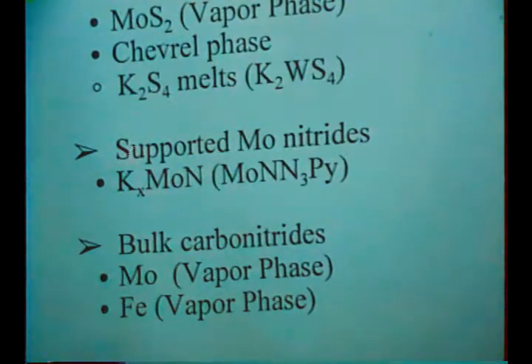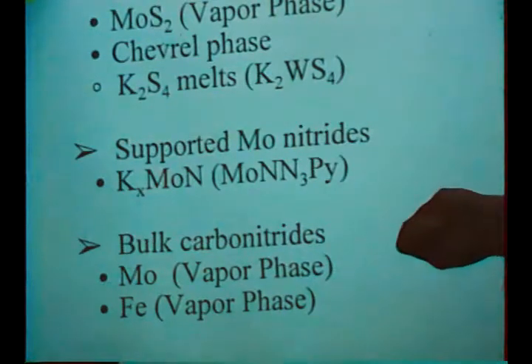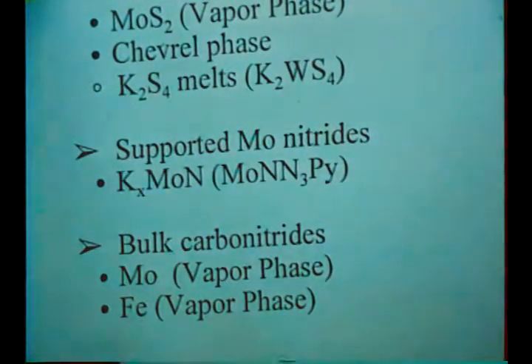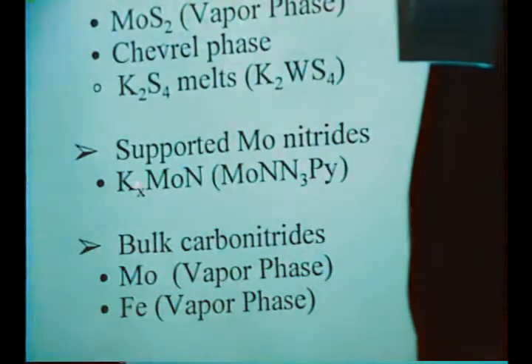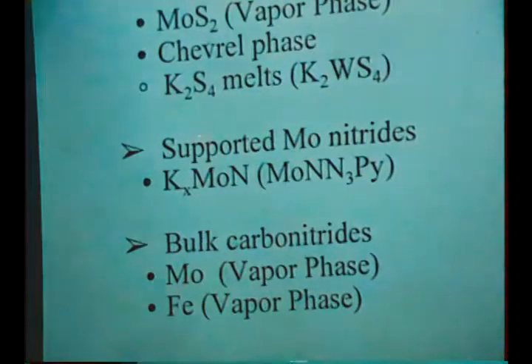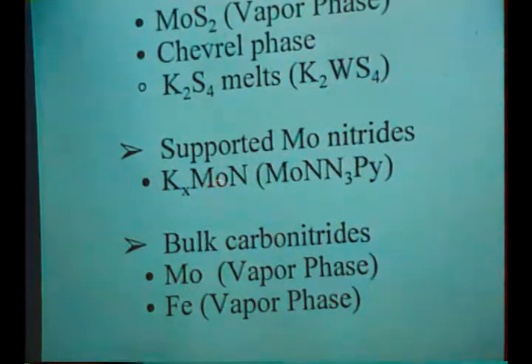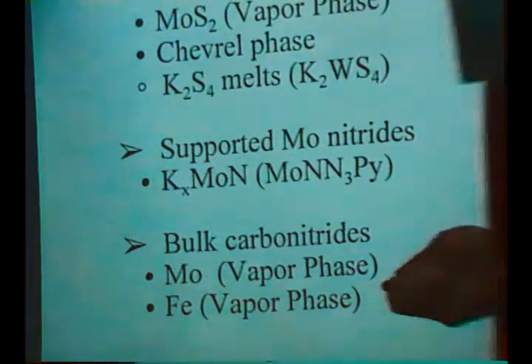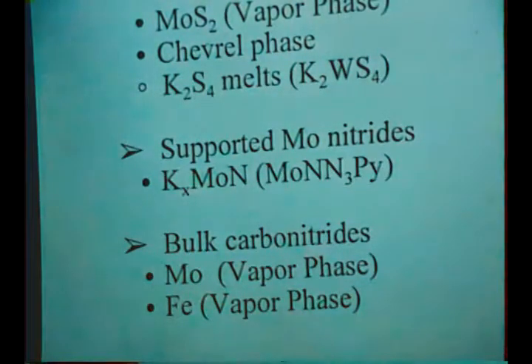The third area is making supported molybdenum nitrides. Now, this process was initiated with some work I did through graduate school with a molybdenum azide compound that is soluble in pyridine dichloromethane that can be then supported on supports and alkalized to make a potassium or cesium doped molybdenum nitride, supported molybdenum nitrides. This is a fairly unconventional approach to the nitrides. Typically they're bulk materials, and these have been evaluated in a preliminary fashion. The last area, bulk carbonitrides, through the vapor phase reactor, I've also been able to make molybdenum and iron carbonitrides, and also the mixed metal molybdenum and iron carbonitrides. And I'd like to talk a little bit more about that in a few minutes.